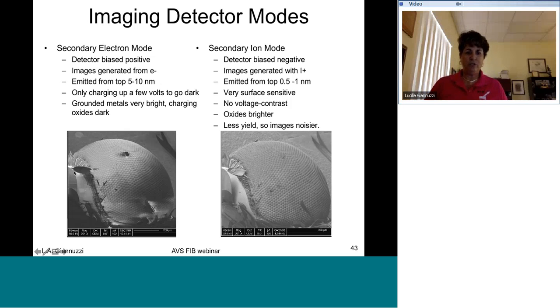So here we see that these different regions here in the lower left and this leaf and some other features on this bug's eye are dark. And they're dark because they're charging, and so any secondary electrons that are generated from this surface are being pulled back down to this surface. They're not getting out because they're charging, and they're not getting to the detector, and hence they show up dark. Conversely, now if we switch to secondary ion mode, these are extremely shallow, emitted from only the top 0.5 to 1 nanometer, so they're very surface sensitive.